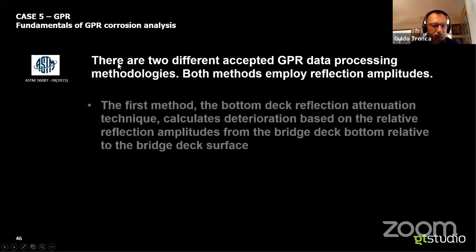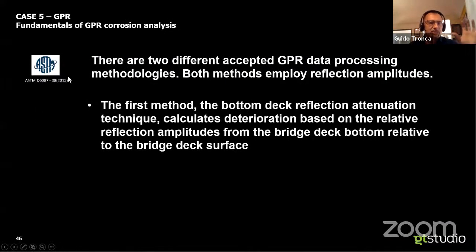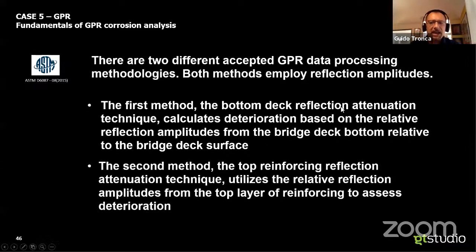On something that is quite well assessed by many of our colleagues at ASTM, stating you want to check a reinforced structure for corrosion with GPR. Take a look, if available, at the bottom deck reflection, and take a look at the intensities of the top layer of the rebars.